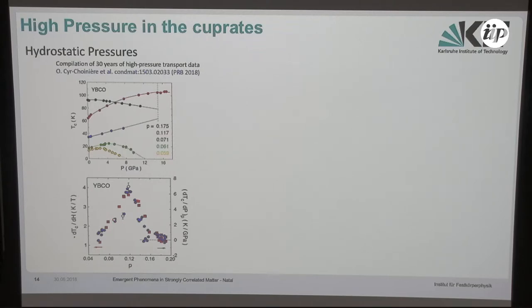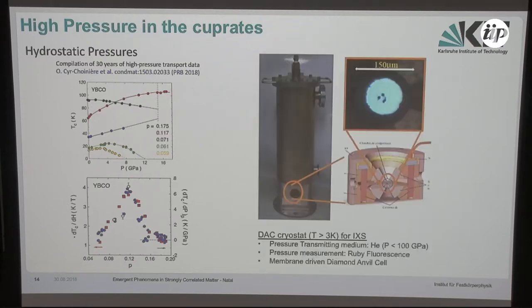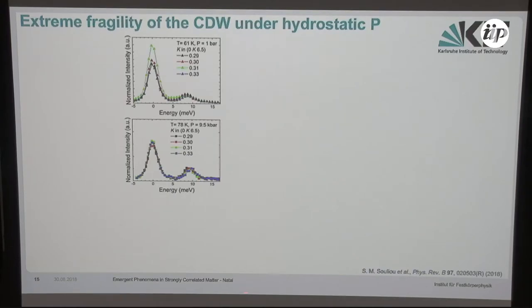So what we did is that we used the cryostat that they had at the ESRF and that they had developed, so we can put a diamond anvil cell at low temperature in inelastic X-ray scattering, pressure up to, in principle, up to 100 GPa. And our idea was to track how the charge density wave behaves under high pressure at low temperature. First, the elastic line that we see here at low pressure, the enhancement is completely suppressed.